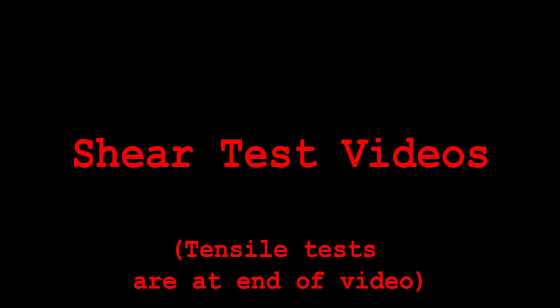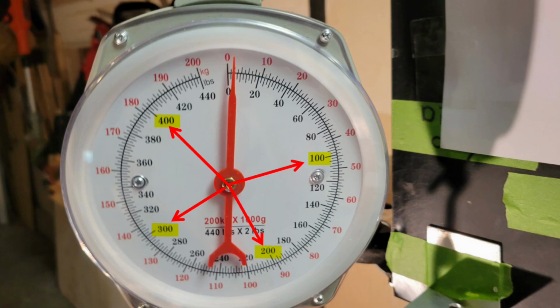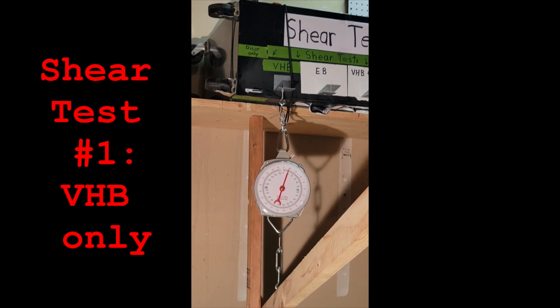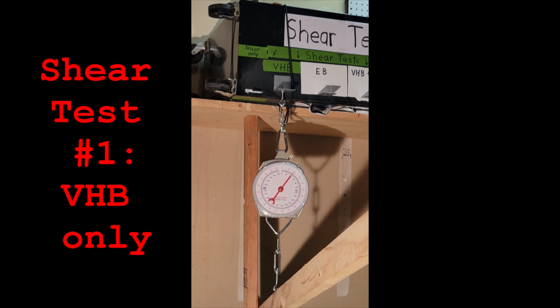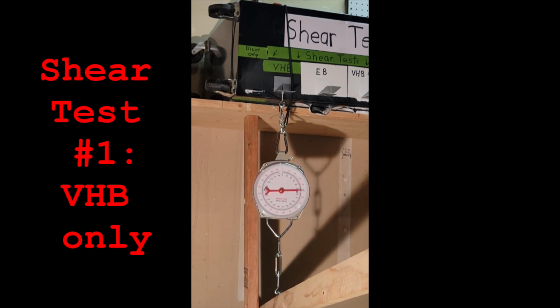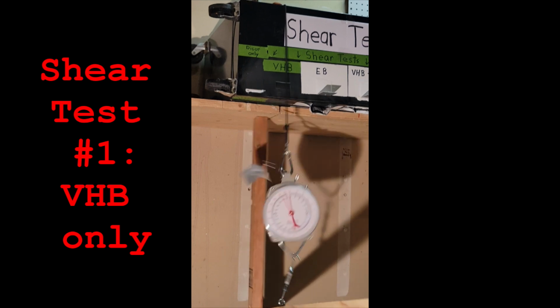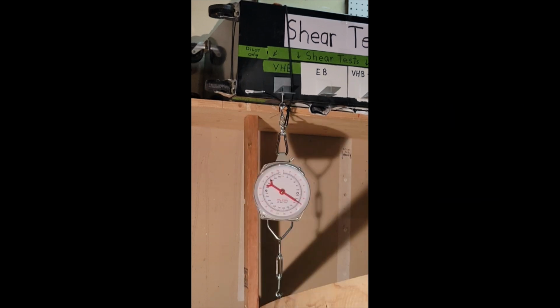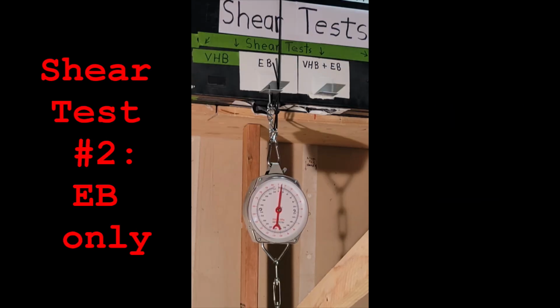Okay, here are the tests. I'll show a freeze frame at the peak force just before failure, since the maximums are hard to see in the videos. Here is the spring scale again, with 100 through 400 pound marks highlighted for reference. First up is shear test number 1, 2 inches of VHB tape only. 134 pounds. Okay, shear test number 2 with the Eternabond tape only.